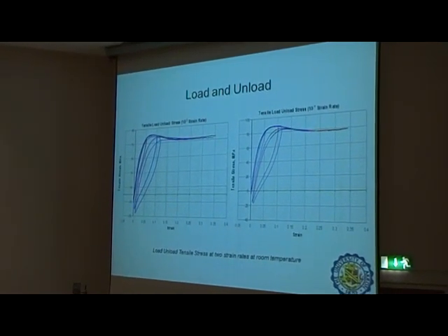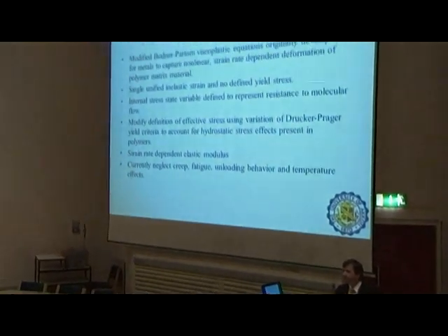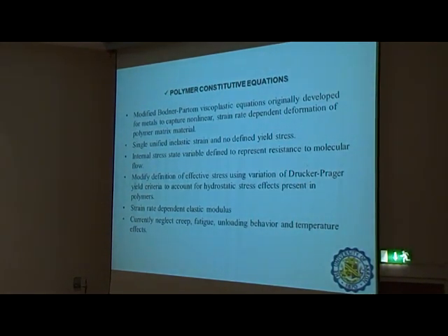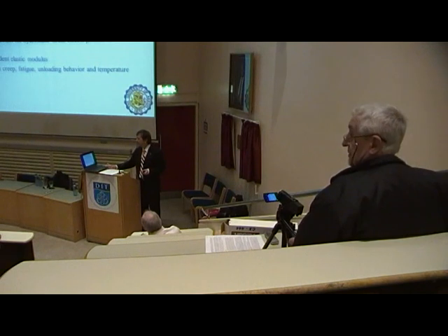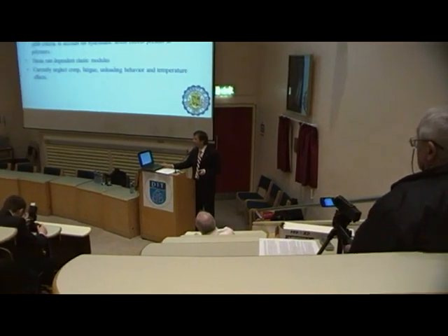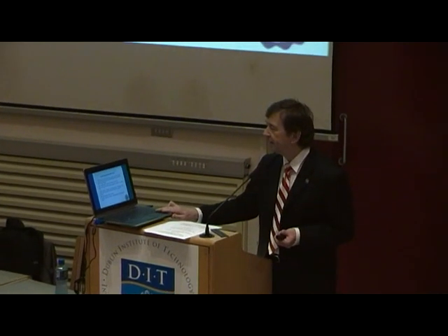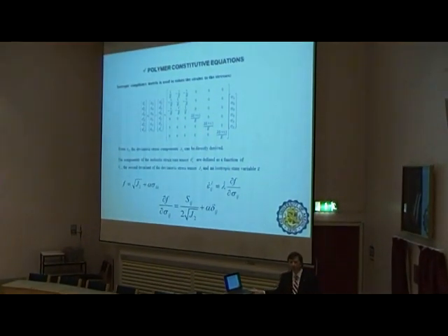Now, because of the viscoelastic properties, if you load and unload, you can get hysteresis characteristics in this test, which means some of the energy is absorbed through just test loading and unloading. And all of that is important because we eventually have to develop a constitutive equation that would describe this behavior of the polymer composite that we use in this material application. So we use the modified definition of the Drucker-Prager yield criterion to account for the hydrostatic stress effect present in the polymers, and strain rate dependent elastic behavior, and basically this is the mathematics that describes the stress-strain relationship using the compliance matrix